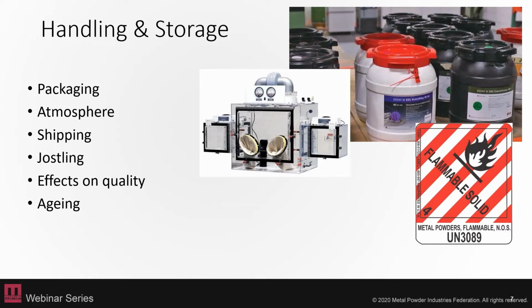When you're shipping, those powders are also going to be jostled around, and those powders then will size segregate within the container based on the motion of that container. And so you need to be careful when you get that powder to make sure that you don't just use the top of that container or the bottom of that container or just pour it out. You need to remix that container before you use it, because that will affect your size distribution, and then affect the quality of your build or your consolidation method.